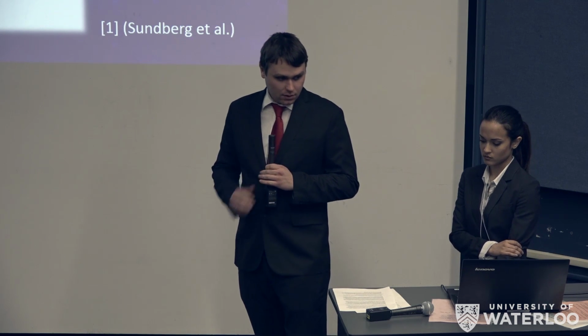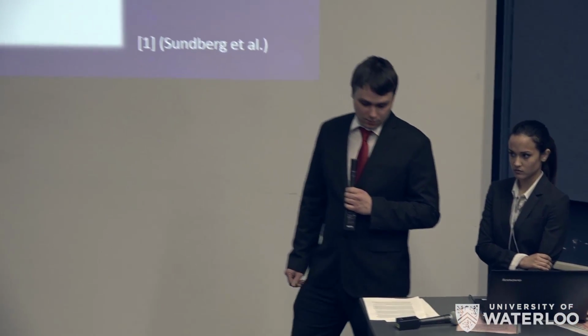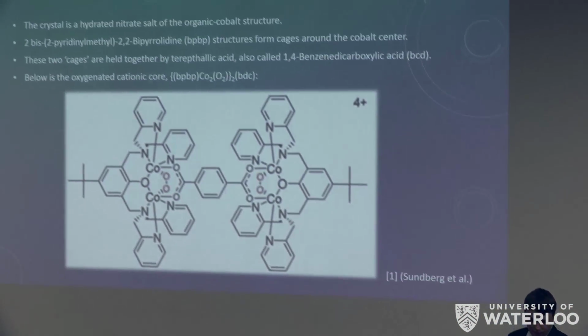Now, the important part of our concept is that when heated to around 80 to 100 degrees centigrade, it releases all of the stored oxygen gas and most of the water. Our prototype uses nanoporous PDMS, as mentioned, to allow oxygen and water vapor flux while preventing the excretion of cobalt or potentially toxic aromatic compounds. The size of the PDMS pores can be selected for the customer's needs. So if water is not desired to be absorbed, you can select pores which would allow oxygen and forbid water transport. The chemistry of our crystal was the main focus of our synthesis and is somewhat complex. The crystal itself is a hydrated nitrate salt of this cobalt metal organic framework.